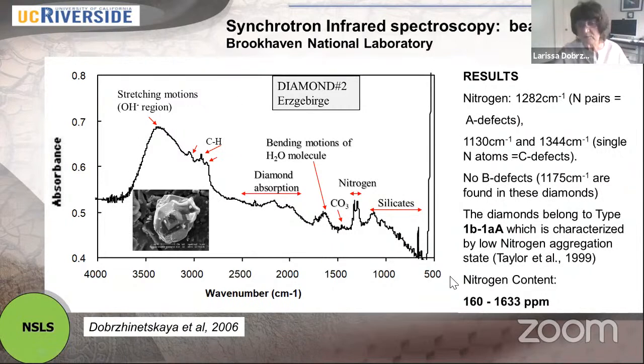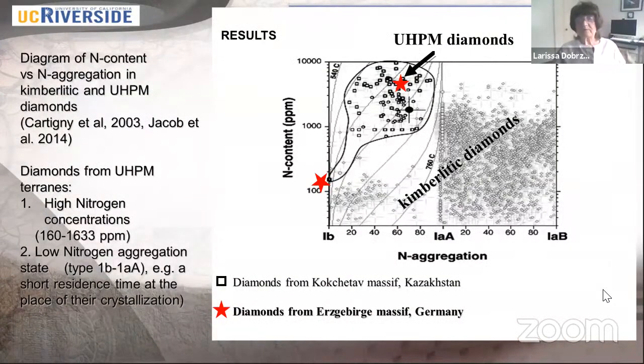We also learned from this research that nitrogen contained in this diamond is about 160 to 1,633 ppm. So let's now summarize this result and see how this diamond can be compatible or different from kimberlitic diamond. For that, we go to a famous diagram created by Cartigny and published in many other papers. We see here nitrogen aggregation, from 1B, small b, and 1AA, and 1AB. 1AB is mostly kimberlitic diamonds, okay? And you see the field of the diamonds from ultra-high pressure terrain. The red stars are data from these two diamonds, which I demonstrated in the previous slides.